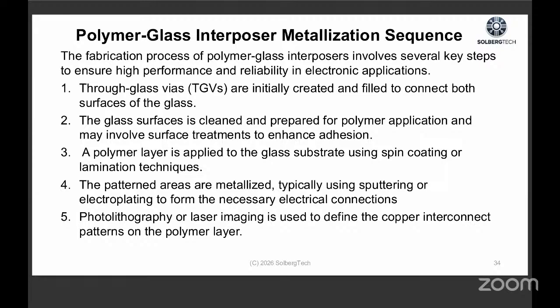And then we use photolithography or laser imaging to define the actual copper interconnect. Now, I got to say that for buildup, there are actually copper coated films, and they can build it up and use a semi-additive process for building the circuit layers to do the interconnect. You could have up to three circuit layers on the surface where we're mounting components. Next.